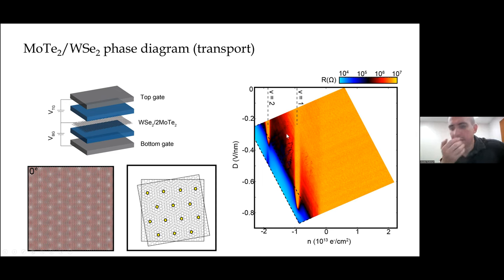And a point that's worth mentioning, I think, is that this system at one hole per unit cell at low displacement field is not topological. It's a trivial system, but it's a very high energy exchange gap. It's well over 100 Kelvin, in a wide variety of these TMD systems.